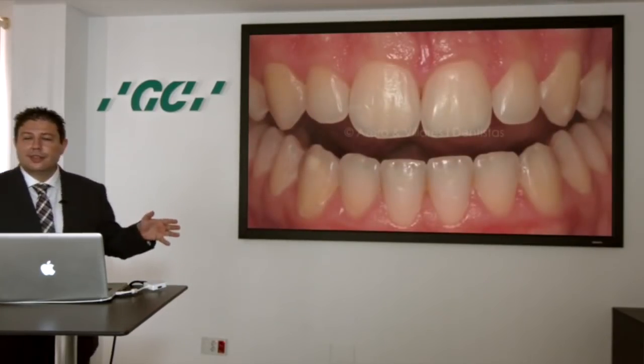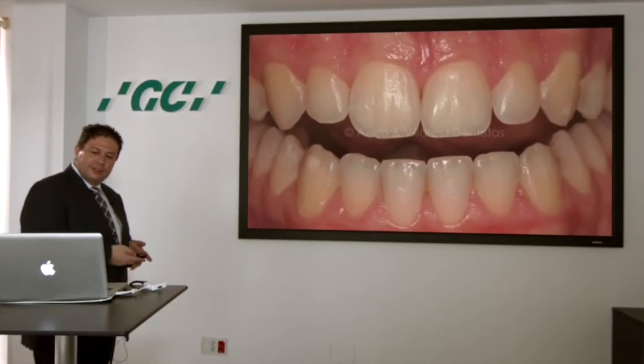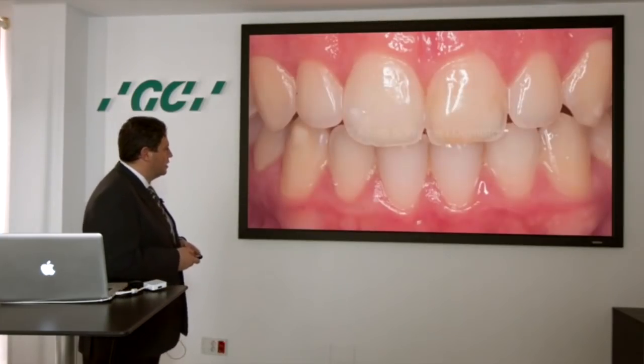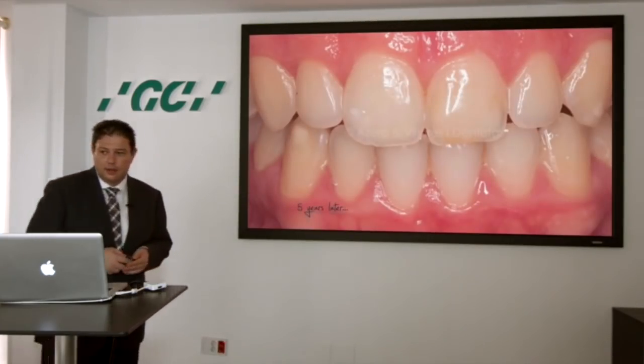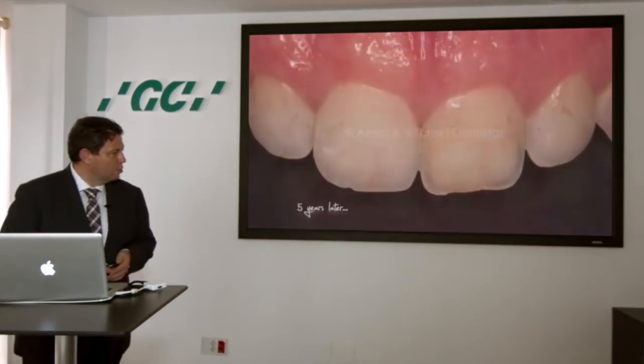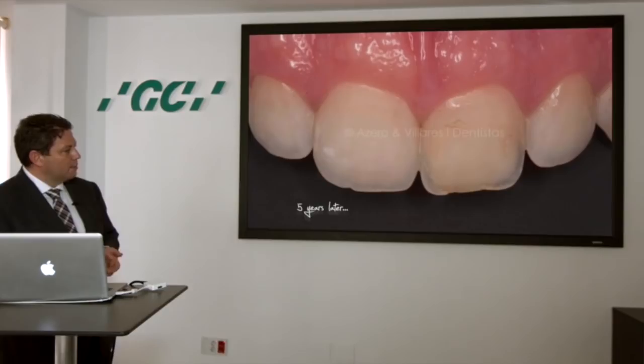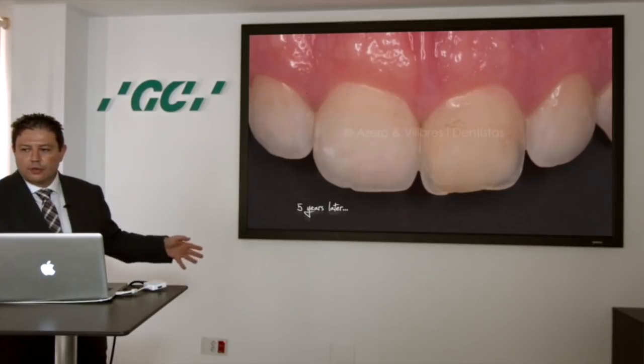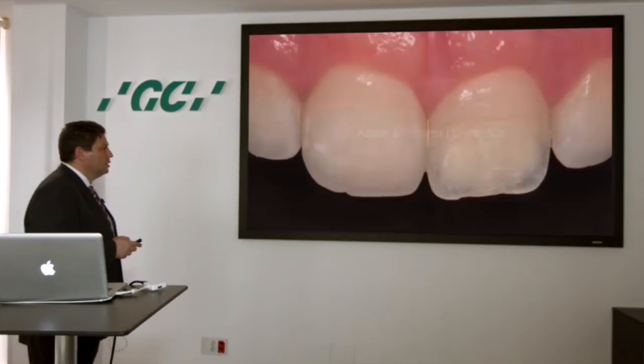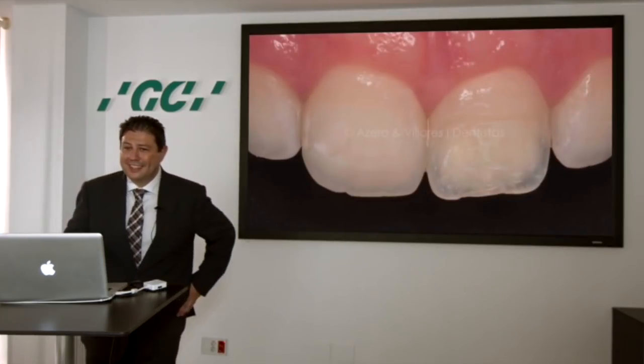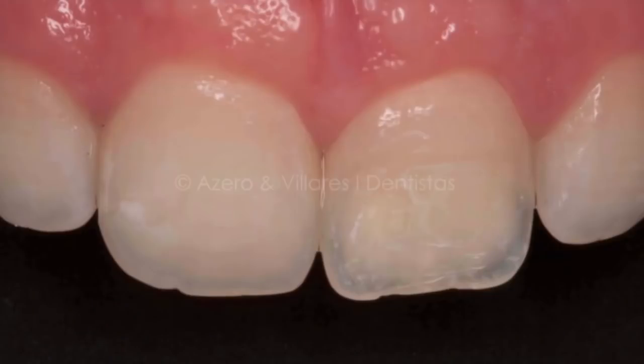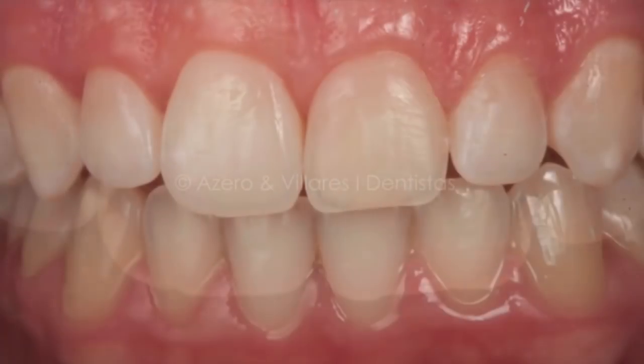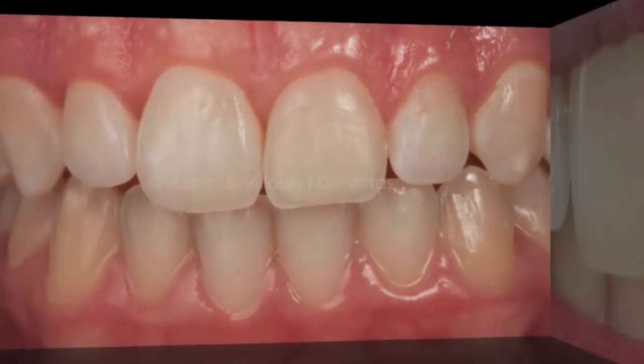But the most important thing is not to see the patient at this moment. You need to see it during the years, and this is the same restoration 5 years later. When we see it in close-up, we realize that we have some problems here. It was a hybrid restoration. So the best thing is composite resin, and we know now that we have better materials, so we eliminate the last layer, we change it, and we control the thickness of enamel, and we can have a very easy result in a few minutes.